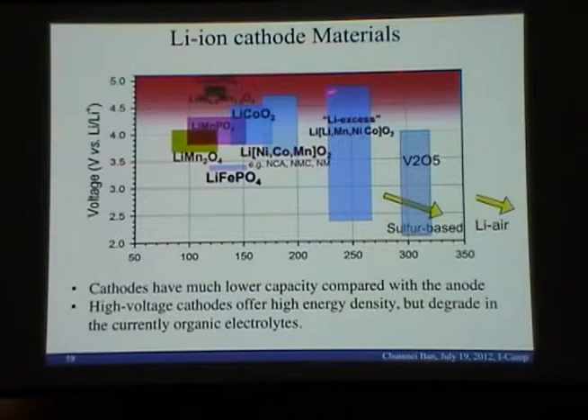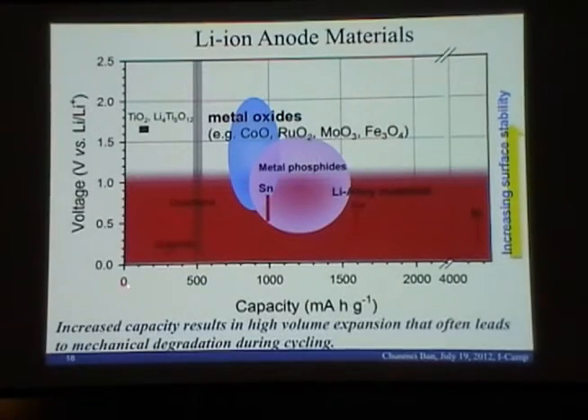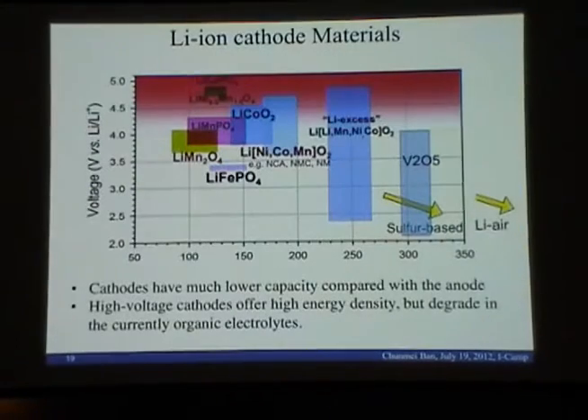So for the cathode part, we do not have many choices. Because see, this scale bar is from 50 to 350. And if you remember in the previous slide, that one's scale bar was from 0 to 4,000. So actually, the cathode limits the capacity of the battery. Once we talk about intercalation, we always talk about one electron intercalation into the structure. For example, lithium cobalt oxide. Actually, lithium cobalt oxide only has 0.5 lithium in the structure. And lithium iron phosphate has 1 lithium in the structure. So that is the reason why the cathode cannot give the high capacity.